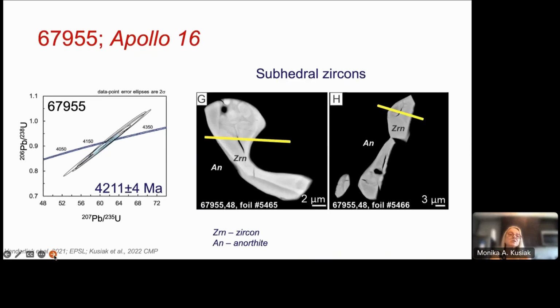In the second sample, 67955, we had two subhedral grains, but take a look, they are really tiny. The scale on the left one is 2 micrometers, and the scale on the right grain is 3 micrometers. And actually, both of these grains were dated. And take a look here, because we can see granular phases as well. This is a little bit different feature. In the previous grain, we have granules which were consolidated together. Here, these are granules all together in zircons.